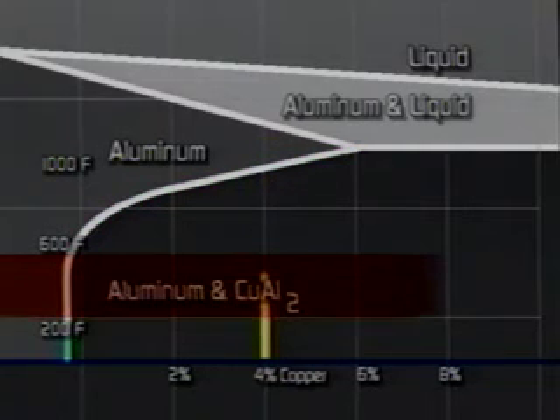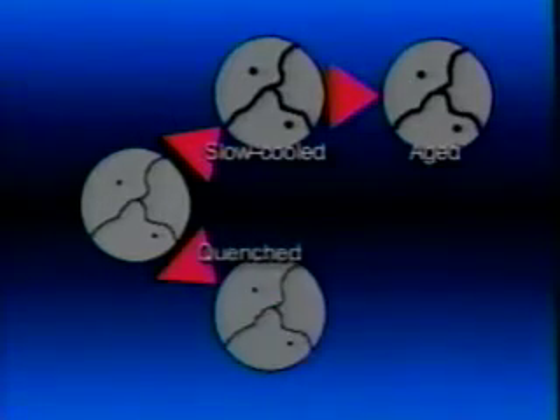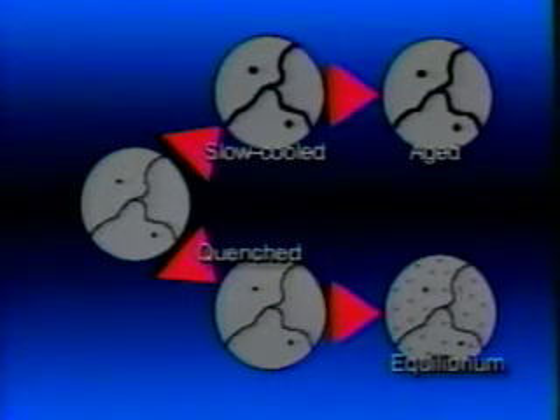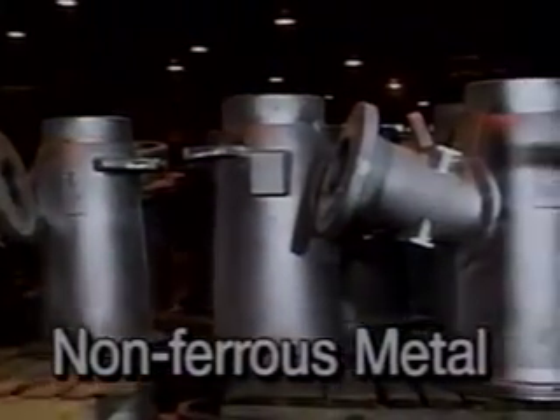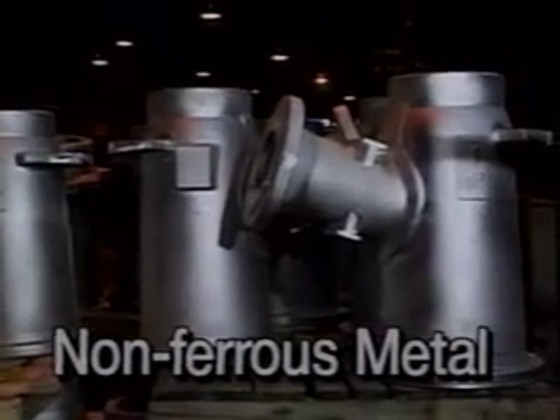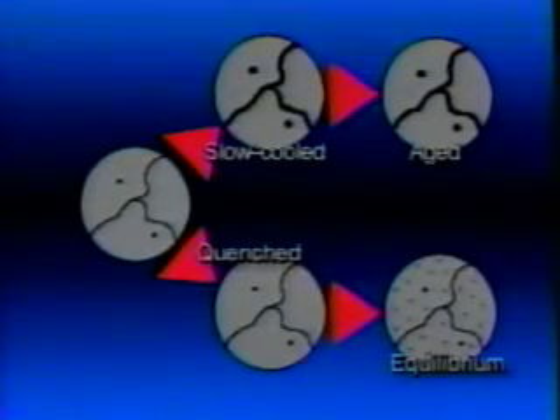Once quenched, a modest heating allows the excess copper atoms to form extremely small clusters that are uniformly distributed throughout the alloy. These clusters are so small that very high-resolution microscopes, such as electron microscopes, must be used to observe them. These clusters retain a definite structural relationship with the parent aluminum lattice. That is, they are coherent with the parent aluminum lattice. In this condition, the alloy possesses high strength and hardness, along with useful ductility and toughness. In other non-ferrous alloys, particles of phases rich in alloying elements need not be as small as those in aluminum alloys. However, the metallurgical phenomena are similar.